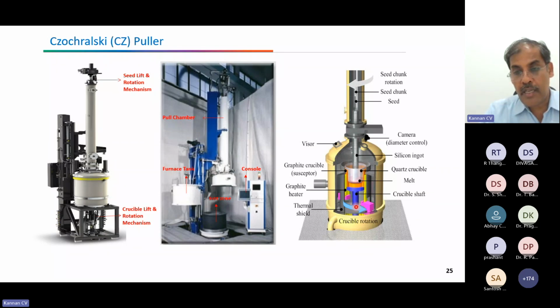If you see here, there is a pedestal where the crucible will be placed, and inside the crucible you put the polysilicon, high pure polysilicon material. During the growth process, the crystal will be pulled like this. At the same time, the pedestal also will rotate. The crucible also will rotate, and the crystal also will rotate opposite to the crucible. That way, you ensure that the melt is uniformly mixed, and you can get a very high pure crystal. So this is the overall schematic view of crystalline silicon growth.